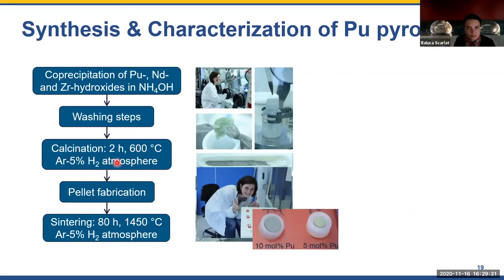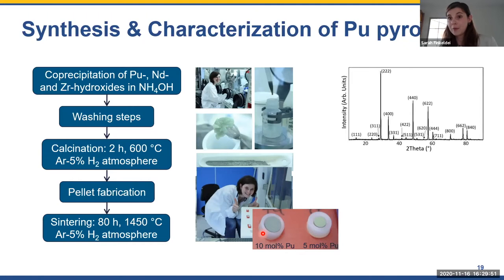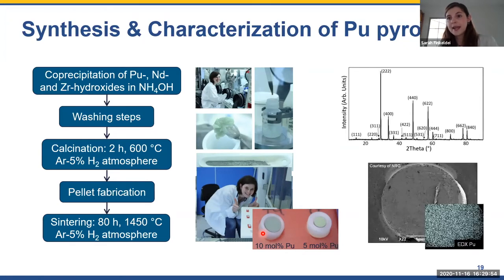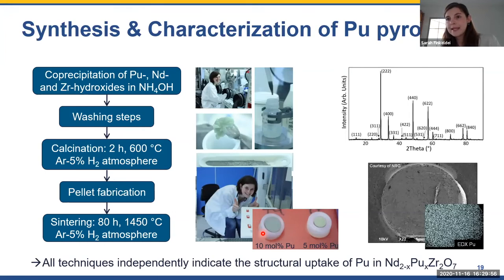So a year later, when I had export and import licenses from the Netherlands to Germany to ship those samples, I went back and embedded those samples, a 5 mole percent and a 10 mole percent plutonium doped pyrochlore, for X-ray absorption spectroscopy analysis, because all the equipment that was available on site, like XRD and SEM, all showed independently a structural uptake of the plutonium. So you would not see any plutonium segregations in our pellets, and we could also index all of the reflexes with a pyrochlore crystal structure.